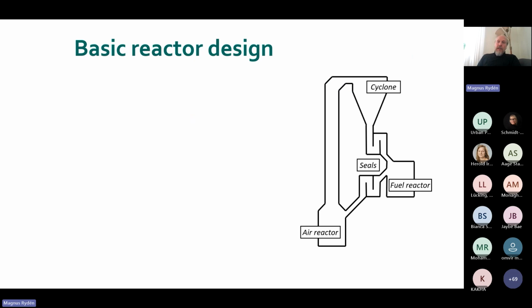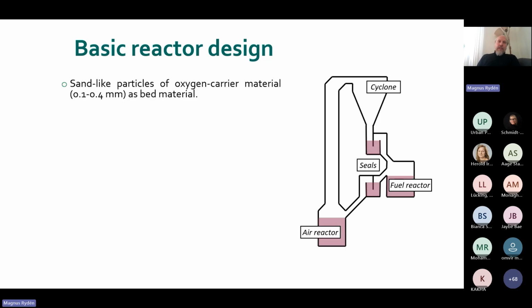And how can you build a reactor system like this? Something like this is the simplest way we can realize it. We have an air reactor, a fuel reactor, a cyclone, and two things we call a loop seal. We fill these reactor vessels, which are fluidized beds, with our oxygen carrier particles, which are in the form of sand-like particles, size perhaps something like 0.1 to 0.4 millimeter.